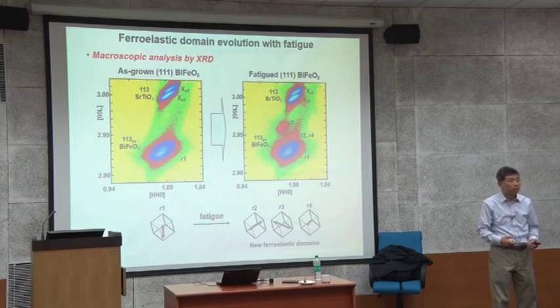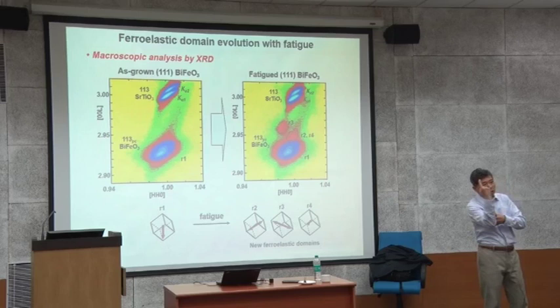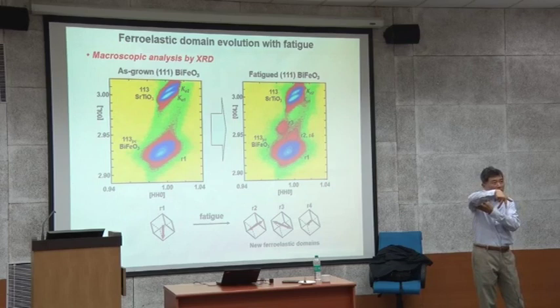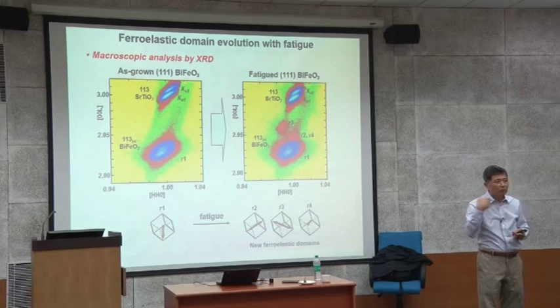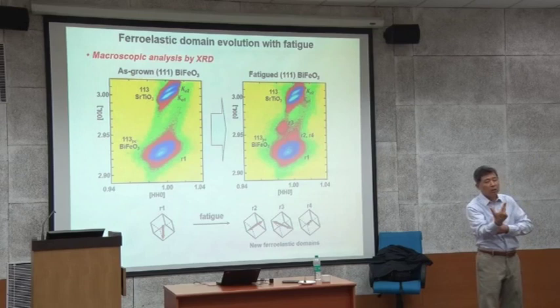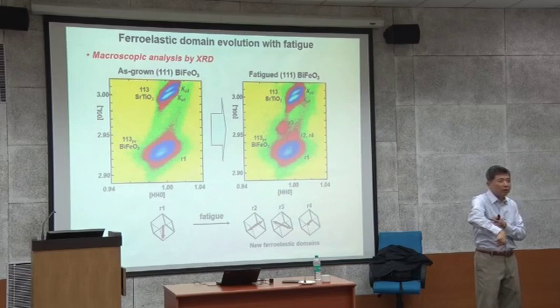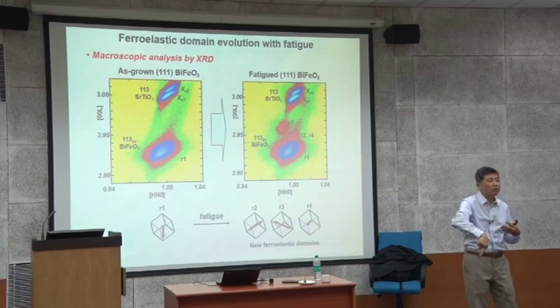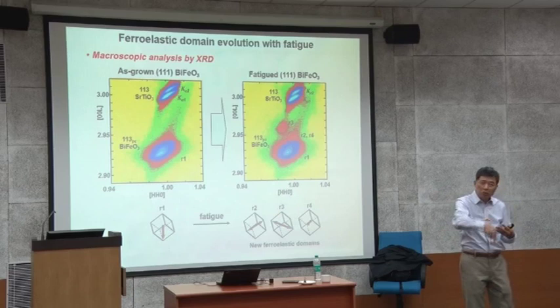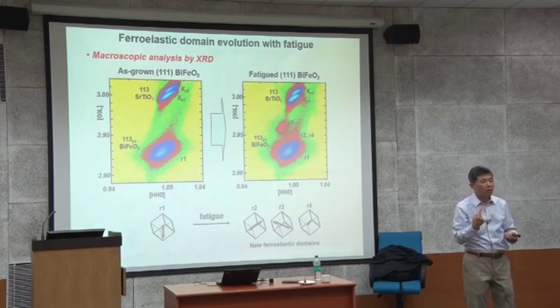What this means is, when you switch from here to here, there's an intermediate state in between. Because of this rhombohedral nature, this is not only BiFeO3; switching in other rhombohedral systems goes that way. So here, here, here, and here. It's not a deterministic one-to-two back and forth. Most people thought all the switching was that way, simple back and forth. That's what people believe. But this data tells us that doesn't happen. What happens is the intermediate state. So somehow you switch many times like this.